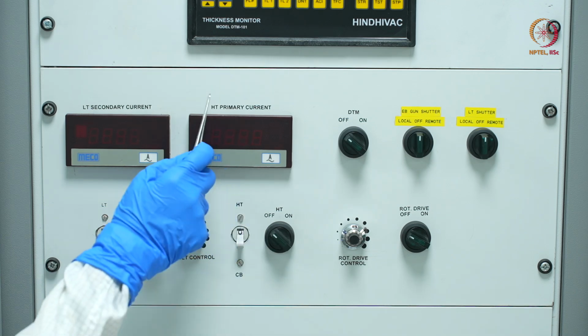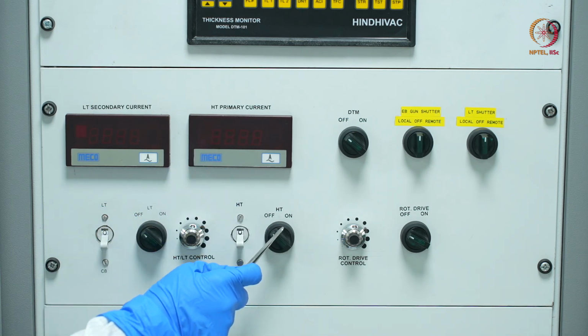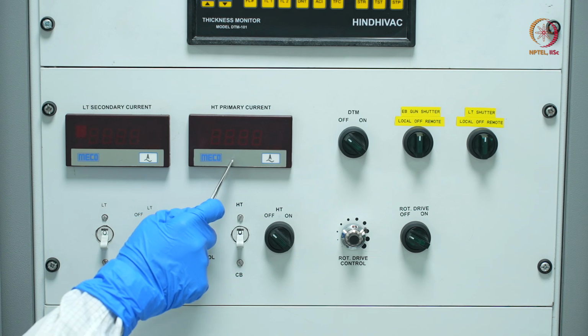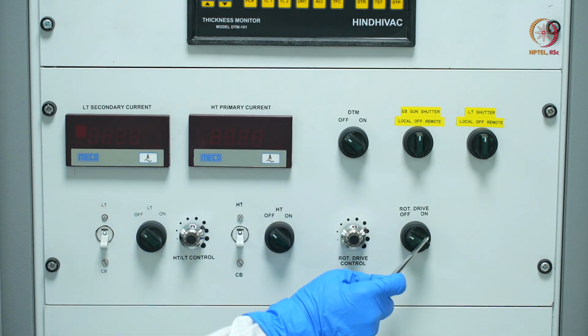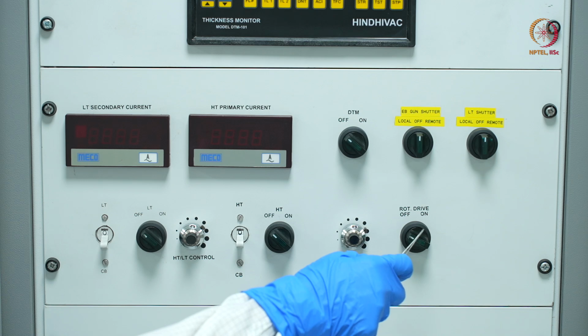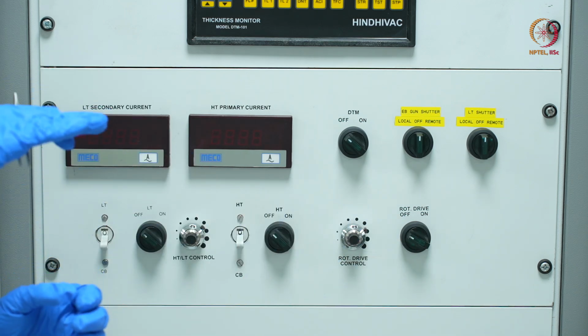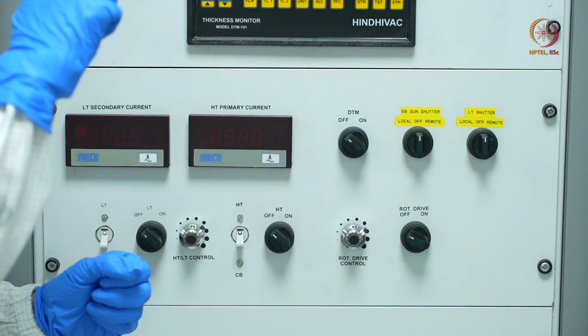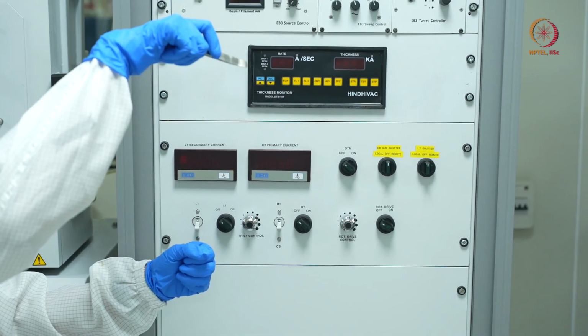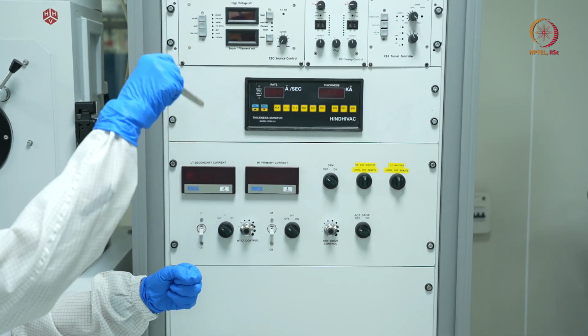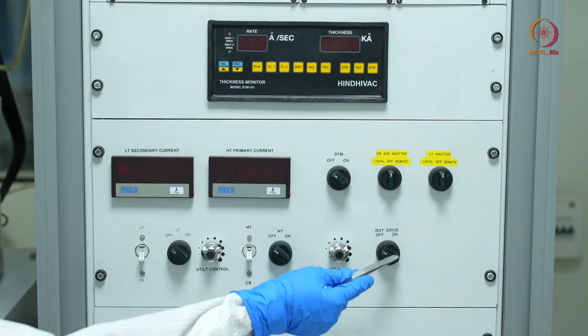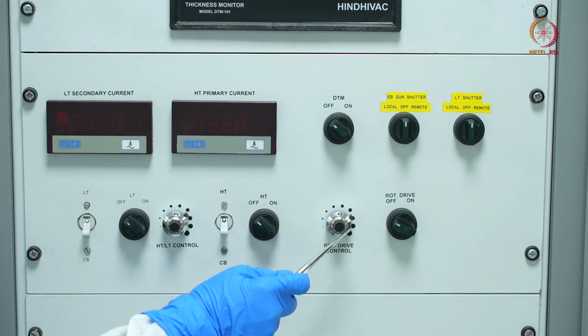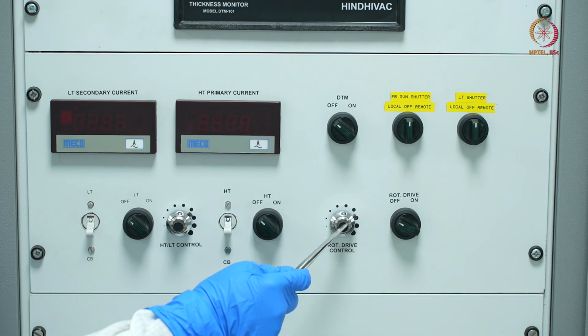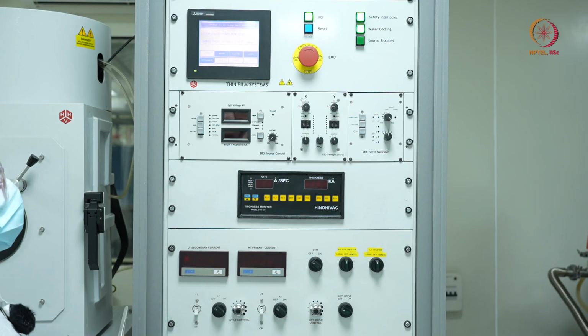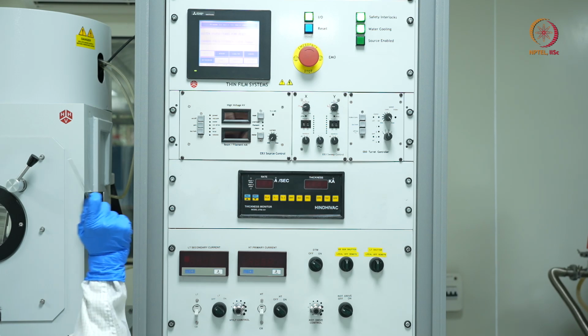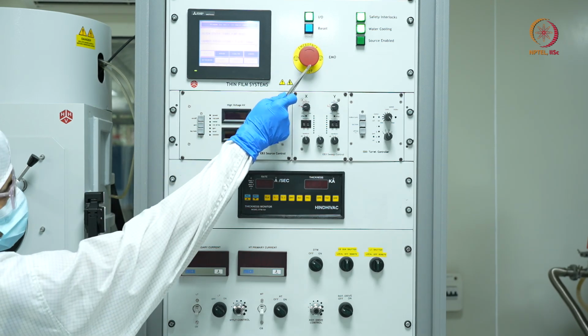Same goes for high tension current. This is a knob to switch on the display for high tension, and this is a knob for the rotary drive, because I want a uniform deposition on my substrate. So I want my substrate holder to rotate at low RPM speed. This is a knob to switch on the rotation, and we can set how much rotation we want using this knob.